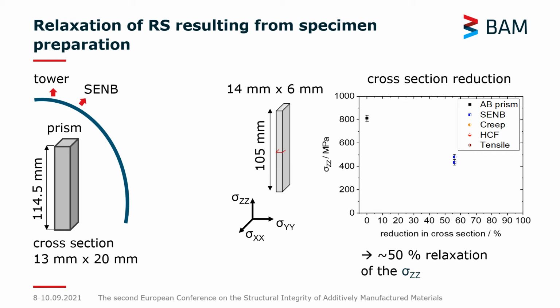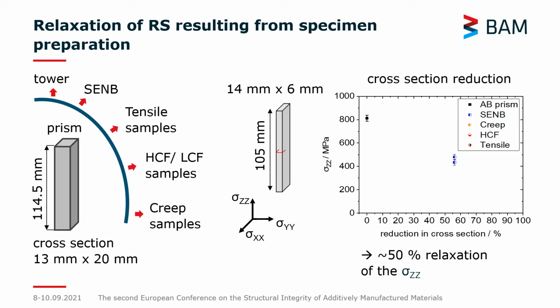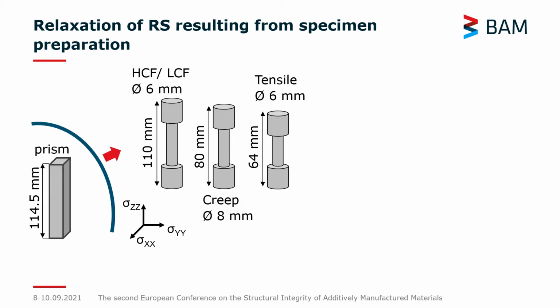I have to note here that these SENB specimens were heat treated before the actual manufacturing of this SENB geometry was performed, but we'll come to the effect of the heat treatment at a later stage. The other geometries we looked at were cylindrical. So from the as-built prisms, we extracted high cycle fatigue or low cycle fatigue specimens, creep specimens and tensile specimens, which had different heights, as you can see, and also the diameter changed.